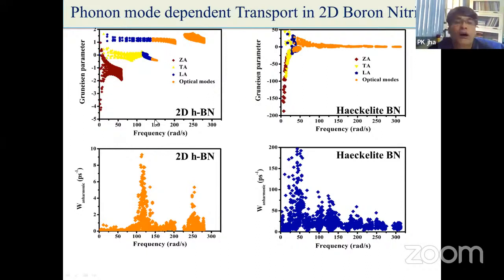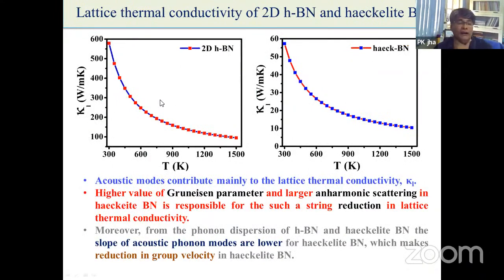When it comes to the Grüneisen parameter, you can see the contribution from ZA, contribution from TA, LA, and optical modes. And here you can see again in the haeckelite boron nitride, the Grüneisen parameter is much higher in comparison to the Grüneisen parameter in the case of 2D. That means one can tune the phonon dispersion curve in such a way so that the Grüneisen parameter, anharmonicity, etc. is increasing, and finally it lowers the lattice thermal conductivity.